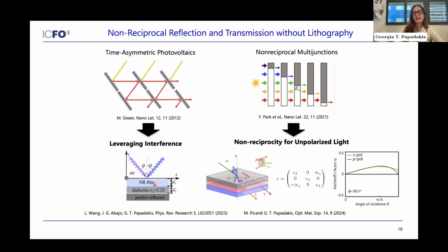And you can see that in this case, one can absorb light from one side and really emit from the other towards the other. And here you can see that in transmission mode, you can do this for both linear polarizations, which is what you would need in order to actually get closer to these theoretical proposals for reaching the efficiency of 93%.